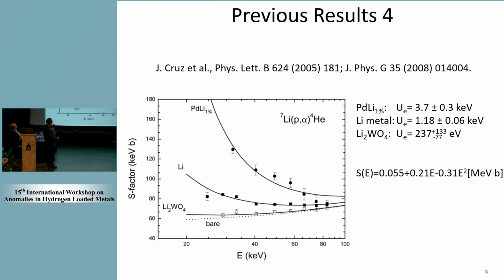They tried to go to heavier beams or heavier targets. This one is with a lithium target, by the Bochum group, and they measured quite a high electron screening potential in the palladium lithium target. What I think is important is that lithium was implanted into palladium by plasma discharge. You should not forget about it. And they got 3.7 kilo electron volts for this reaction with lithium. They also went on to measure higher Z beams or targets, but some of those papers are completely wrong. I spent 3 years trying to repeat those, and don't try.